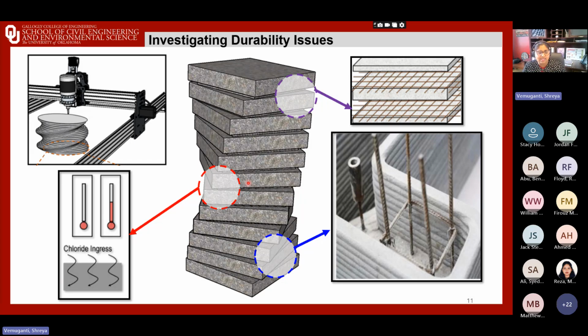If you look at each of these interfaces and you're placing reinforcement either at those interfaces or within the element itself, there is a possibility that temperature changes and chemical or chloride ingress could damage the interface. And from there, microcracks and severe cracking can evolve. So we are exploring ways to embed reinforcements directly. There's a huge push for that in these interfaces. That's why we would like to know how we could use this, but still address any durability issues or even understand them at this stage.